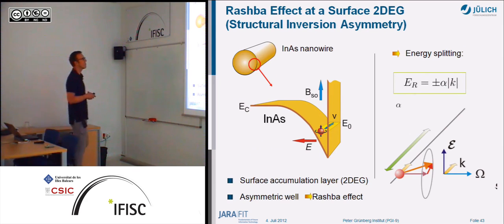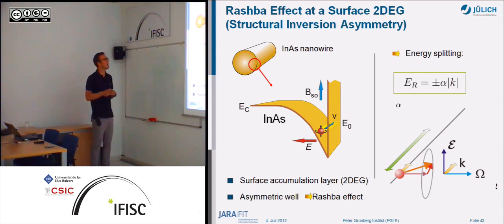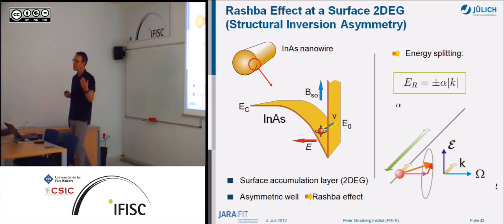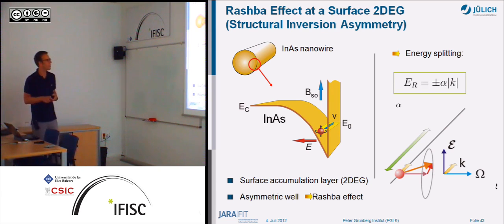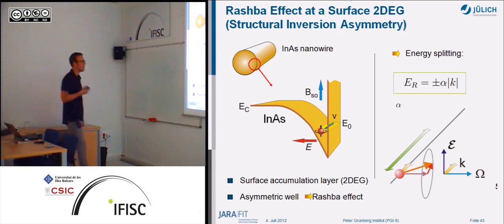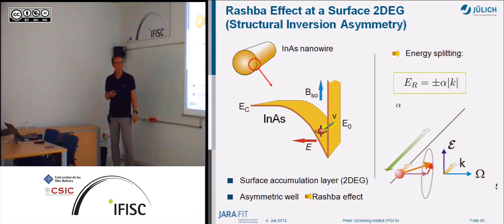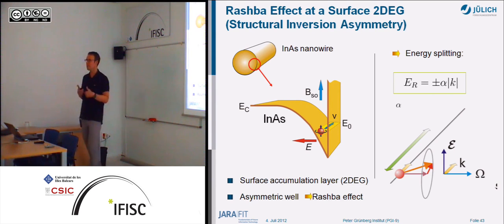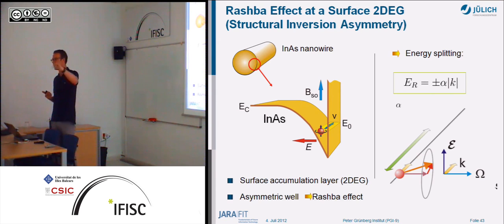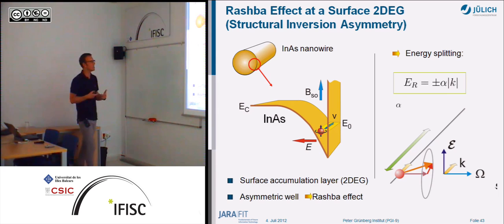If you look at a typical indium arsenide nanowire, I told you that you have this surface accumulation layer, so you have a triangular potential well here. And that's what you need for the Rashba effect. You need some asymmetry in the potential, some electric field here, and if the electron is moving in that electric field, it effectively sees some magnetic field, and then it matters which spin direction you have, so which energy you have. Either you have spin up or spin down. And so this gives you the spin precession, and that's the basis of